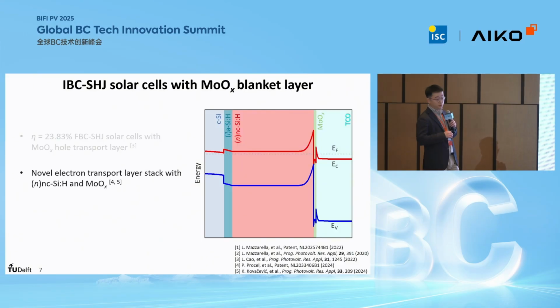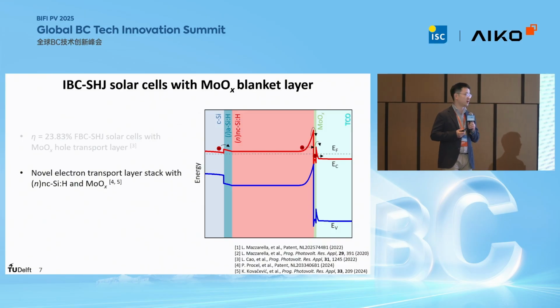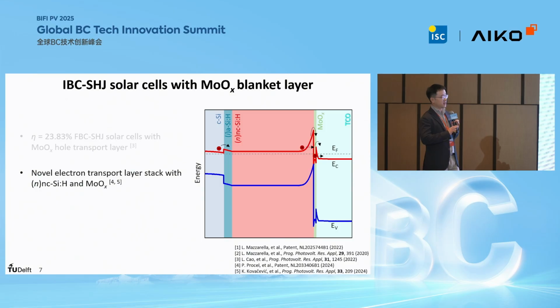If we take a closer look at the band diagram of such a contact stack, when electron-hole pairs are generated in the silicon bulk, the electrons are transported to the intrinsic layer and N-type nanocrystalline silicon layer. The electrons reaching the interface with the molybdenum oxide can either tunnel through or go through thermionic emission to the molybdenum oxide layer and eventually be transported to the TCO layers. Unlike the tunnel IBC that involves a tunnel recombination junction, in this case all the electron transport happens through the conduction band, so there is no recombination process happening.